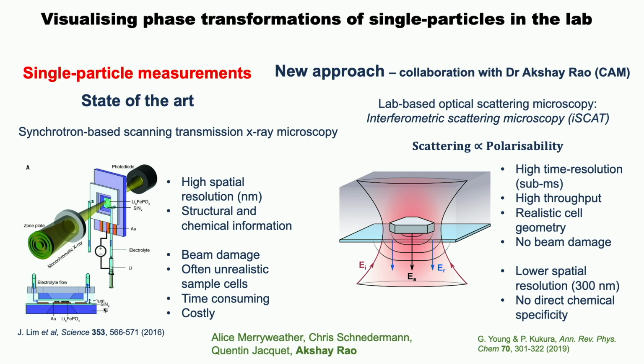Here we're just going to use this method to look at scattering of a particle. Now scattering is proportional to polarizability, and the degree of scattering will be dictated by the differences in the polarizability of the two media. So if you've got a particle, it will be the difference between this particle and the medium around it. It'll be lower resolution. We've got resolution of the order of 300 nanometers. It's a little bit better now, but we don't have any direct chemical specificity.